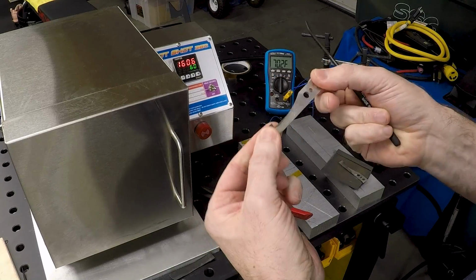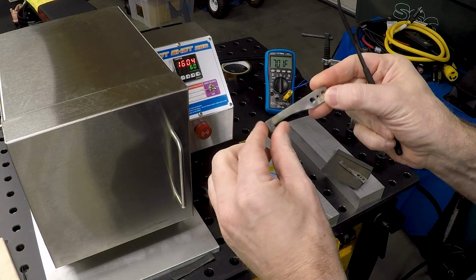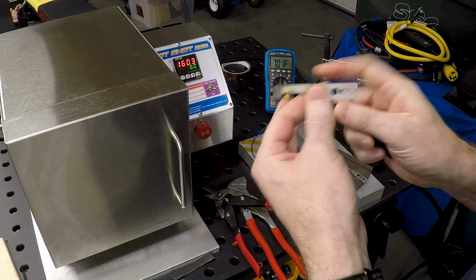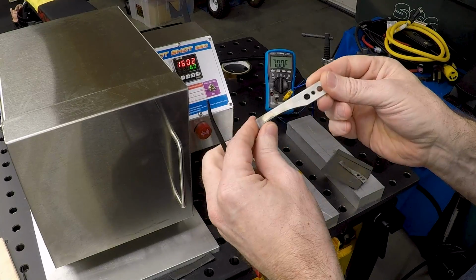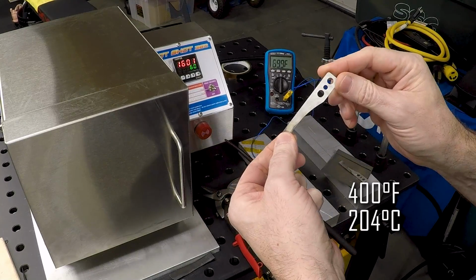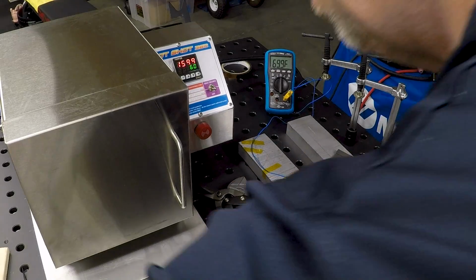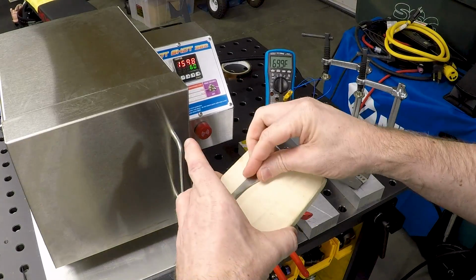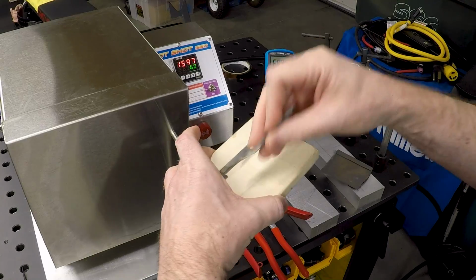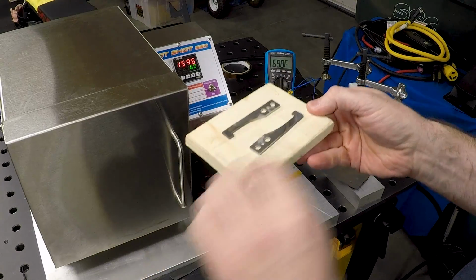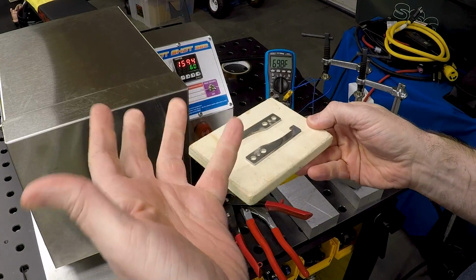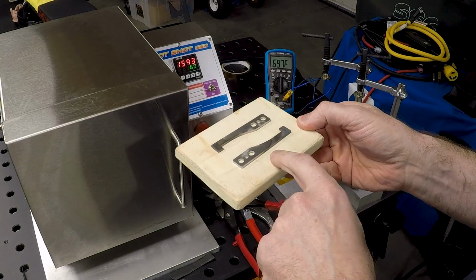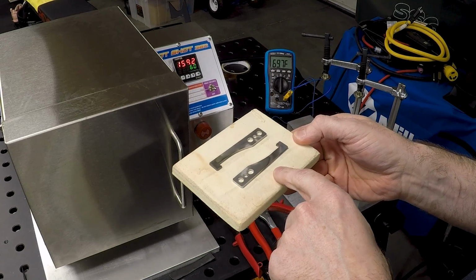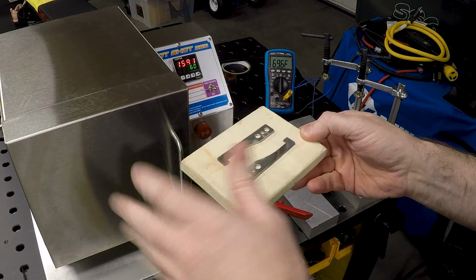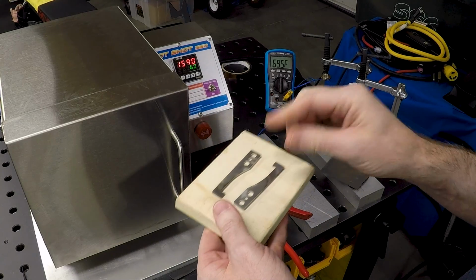Okay, these need to be tempered and then they need to be ground to the final thickness. I'm going to temper these in the kitchen oven. I'll just put these in at 400 degrees Fahrenheit. Just set them both on a tile. Put that in the oven in a cold oven, or I probably put it in a warm oven. Temper these at 400 degrees Fahrenheit for a couple of hours, then just turn the oven off and let them cool, and then we'll be ready to grind.